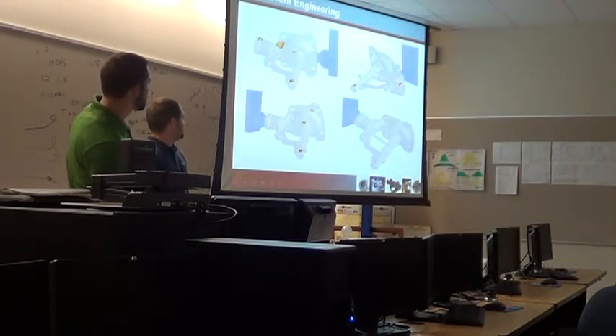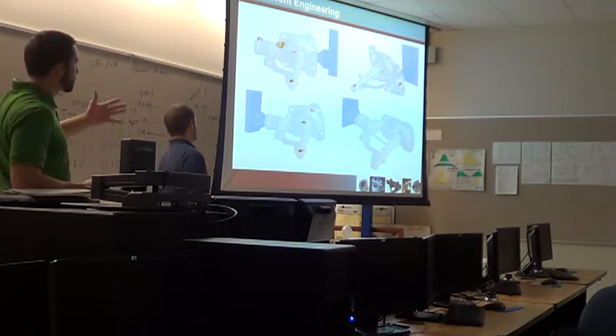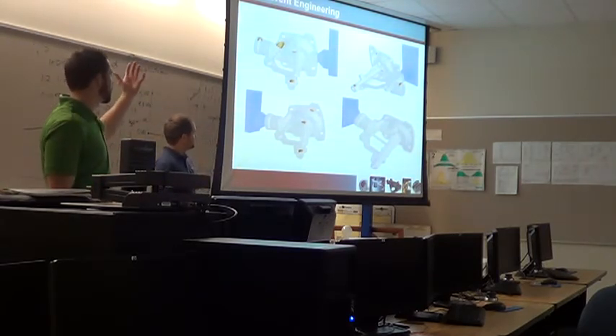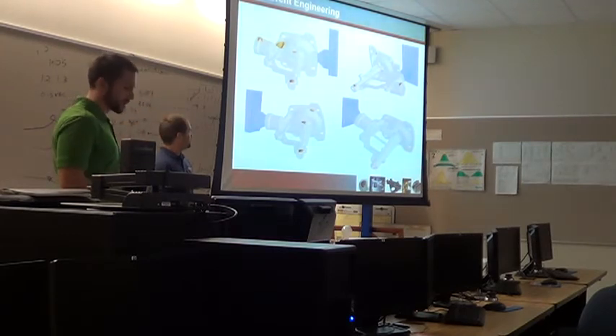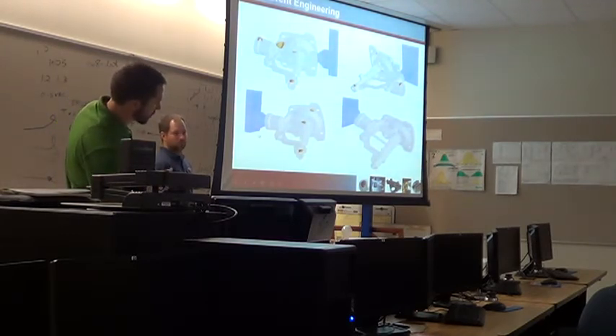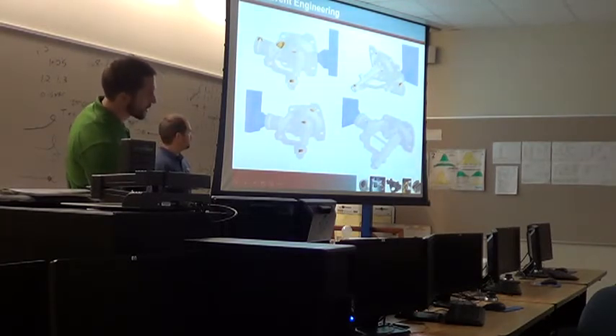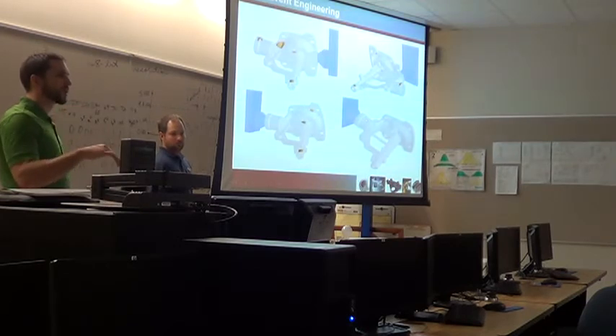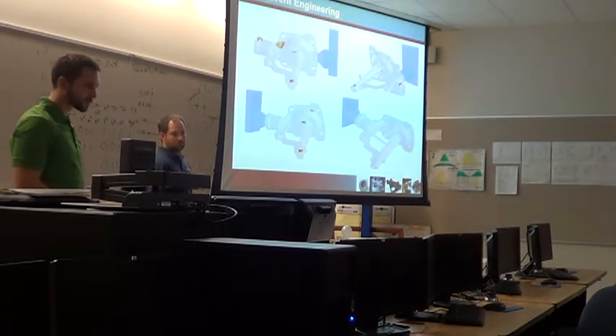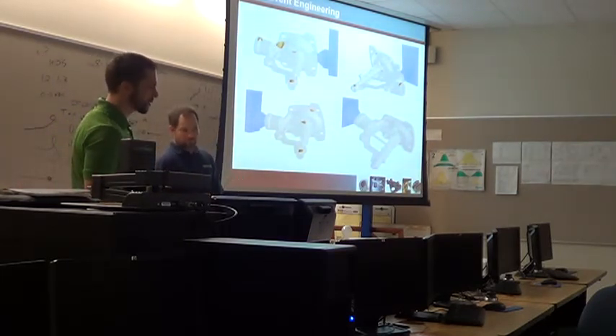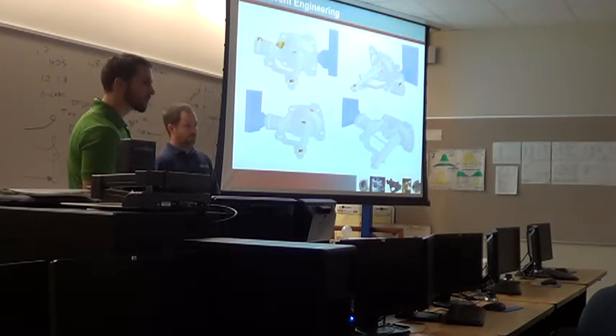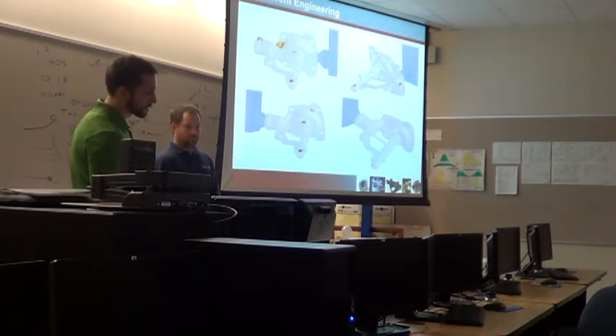Switched it to gating at the boss, and now you can tell the orientation that the mass is above the gate. So if you envision the pouring cup being at the top of the picture, and in this view, your molten metal is flowing down, but you still have mass up here, so your high points have shrink in them. When you rotate the part 180 degrees, now all your mass is below your gate contact. You're allowing gravity to help you out in this case. You don't have high spots above the gate, which is your feeding path. You're not feeding uphill. Beefier gate too. Yeah, we've increased the gate, a little bit of redesign there, but still feeding in the same location.